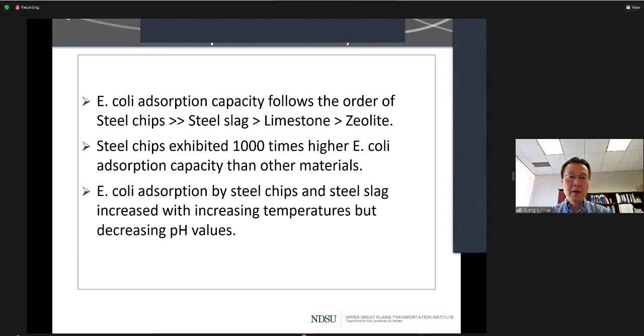And this is the summary based on the batch experiment. First, perhaps the most important, we identified that steel chips are much more efficient than steel slag for E. coli removal, and the steel slag was better than limestone and zeolite. So this is the order of the removal efficiency among the four tested materials. And also steel chips exhibited at least 1,000 times higher E. coli adsorption capacity than other materials. And also environmental conditions can impact E. coli adsorption, and the adsorption typically increases with increasing temperature, but decreases with decreasing pH values.